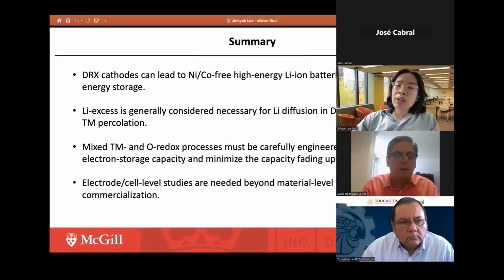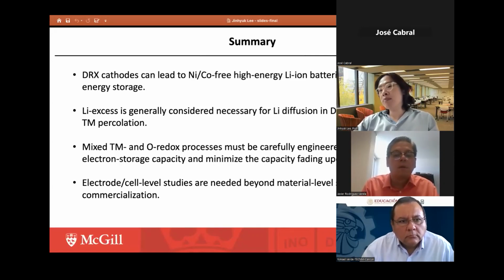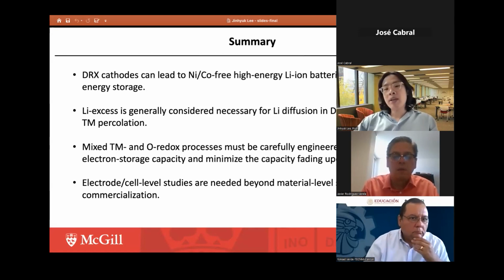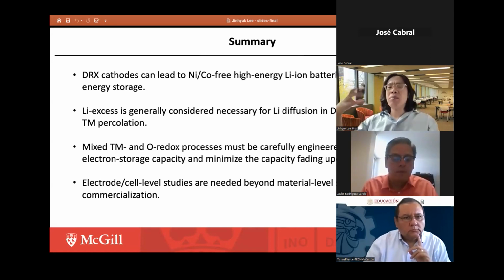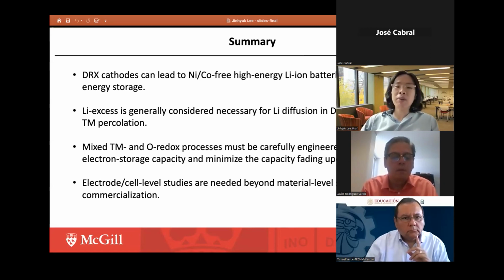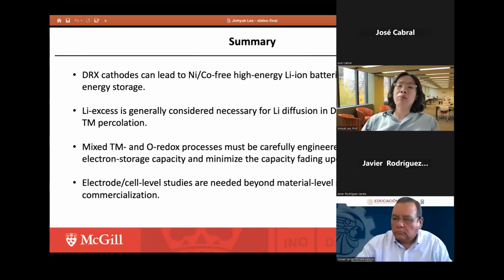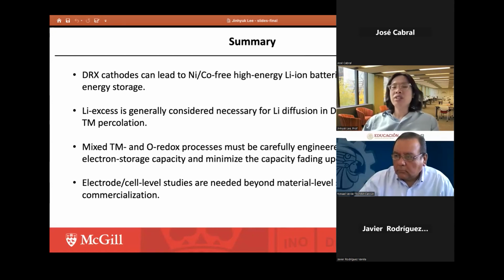If you make a diluted electrode with a lesser amount of active material, you can increase the thickness much larger. But if you start making an electrode film with a higher active material content, then a large thickness may not be preferable. There are a lot of complicated issues happening at the electrode film level, so it is difficult to say what is the best thickness. But so far, we can go up to, let's say, 40 micrometers, or even 60 micrometers. So I think that's possible.